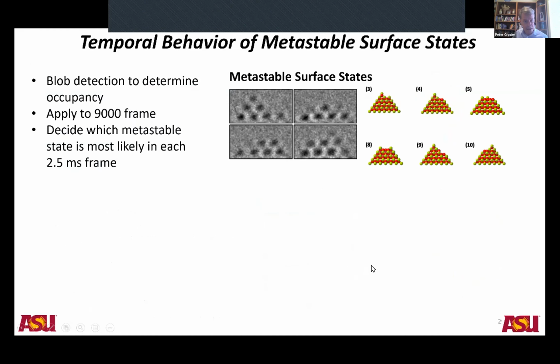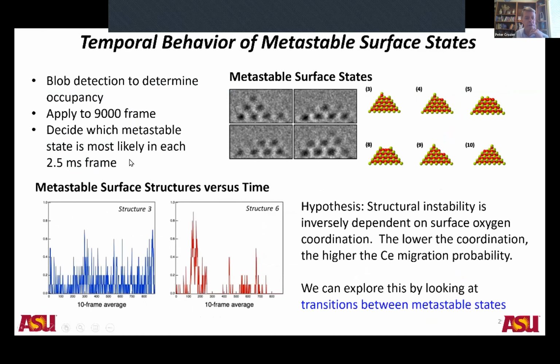And then he can take his videos, which have 9 and 10,000 frames, and he can then analyze using blob detection. He can figure out which metastable states are present or most likely to be present in each 2.5 millisecond frame. And so here now what I'm showing you is just the presence of a particular state as a function of time here. So this is structure 3 and structure 6, and you can see that different metastable states come and go at different times during the movie.